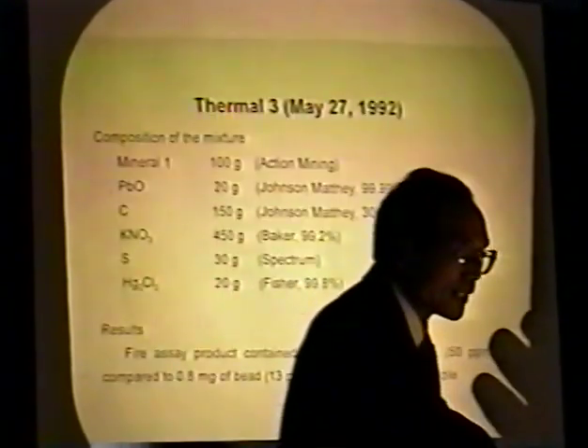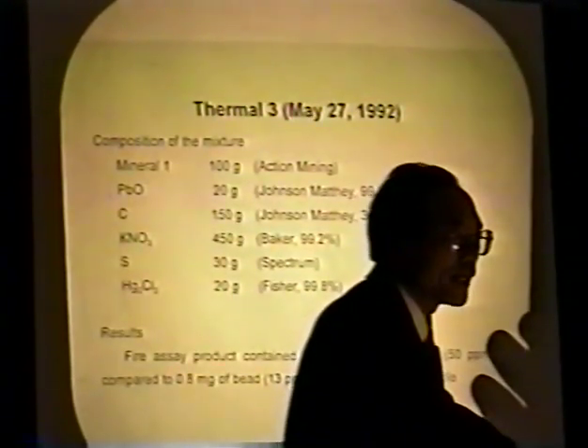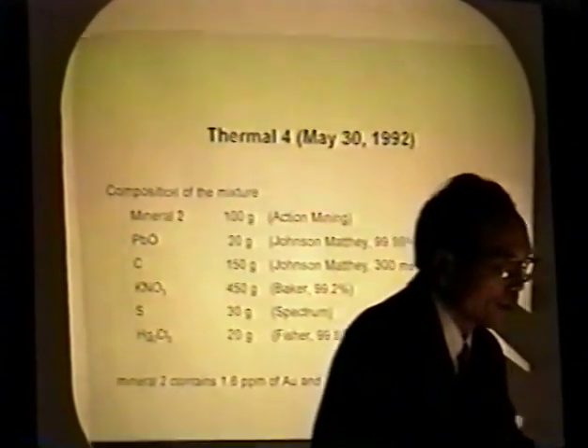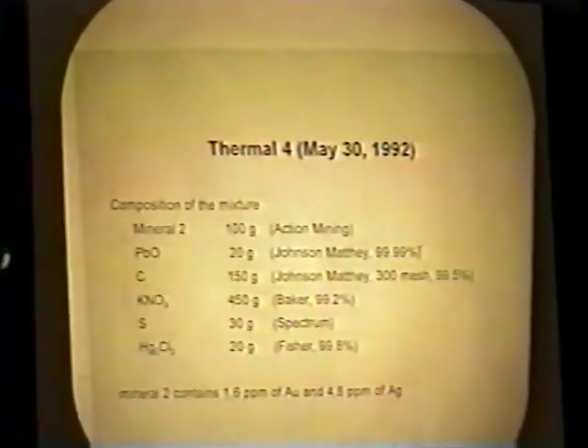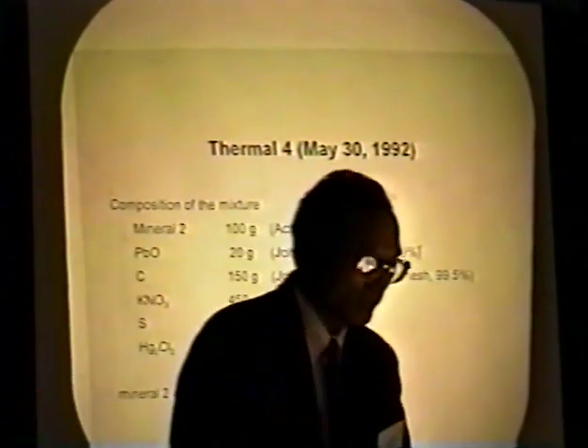Now there's no more analysis for this experiment. Thermal 4 is exactly like Thermal 3, but we use Mineral 2. Mineral 2 is sand containing 1.6 ppm of gold and 4.8 ppm of silver. So in 100 grams, there's 1.6 and 4.8. That's different from Mineral 1.